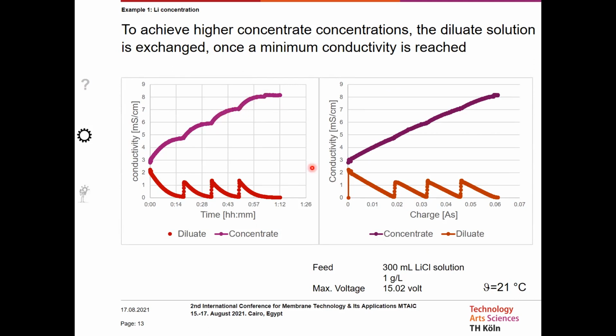And another way to describe this process is not to use the time, but the electric charge. And when we look at the electric charge as a function of the conductivity, then we can see that we come to a nearly linear slope, and this is according to Faraday's law. So this is what we can expect, that until a certain concentration of the lithium, we have a linear dependency of the conductivity and the charge.